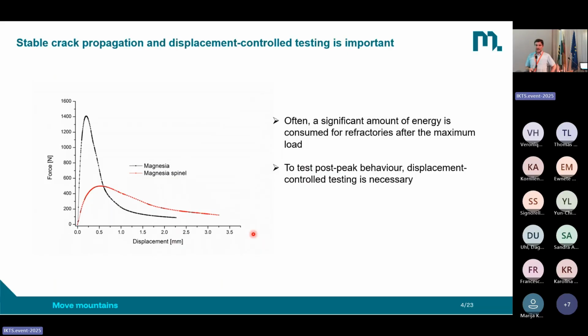But first of all, I would like to discuss with you a curve like you see it here. We have a force and a displacement. This is a result from a fracture mechanical test. What we see, we start at the beginning, then we increase the displacement, we record more force, and then for sure we have a maximum. We reach it, and we further increase the displacement, and then we see that the necessary force for the further displacement is decreasing. So why is this important? What we see here, the area under the curve, is the energy which is consumed for the fracture process. And main part of the energy is consumed after the maximum of the load displacement curve. So if we would like to have an accurate representation of the energy consumed for the fracture, we need to register the whole curve.